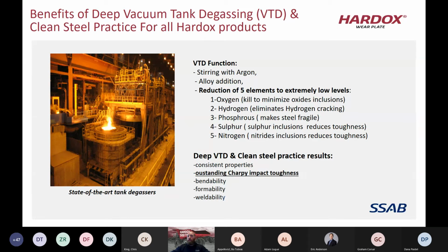One of our process routes is called the vacuum tank degasser. What that does for us is it helps us to really reduce 5 of the big elements that can cause issues to the workability of the steel. One of those being oxygen, there's hydrogen, phosphorus, sulfur, and nitrogen. Now these all can lead to inclusions, cracking, and also reducing the toughness of the steel.